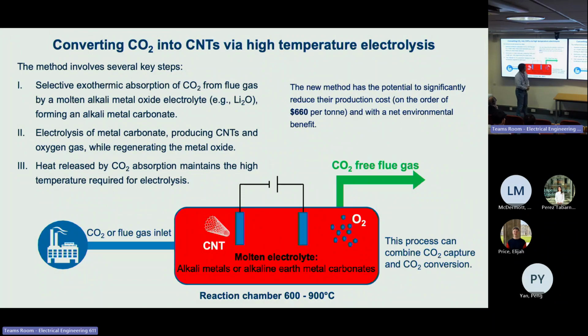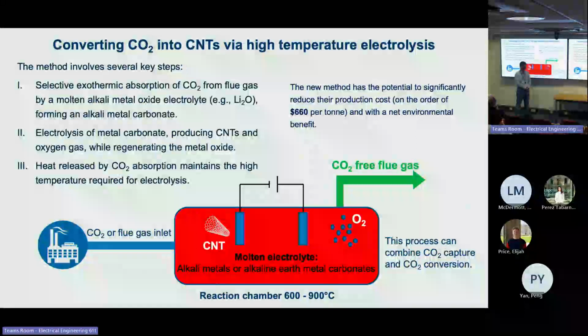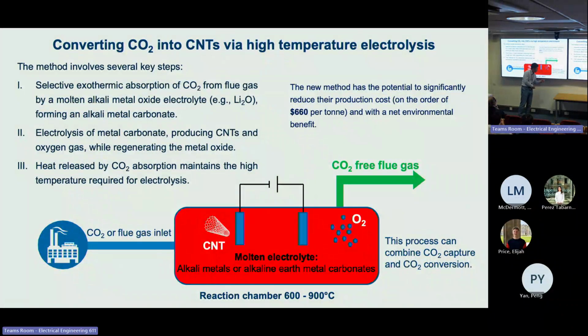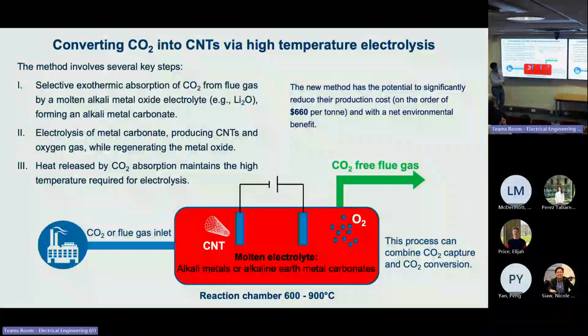So this new method has the potential to significantly reduce the production cost, on the order of $660 per ton. So we can say it's much less than CVD-produced carbon nanotubes. And also with a net environmental benefit, because we are consuming CO2 in this process. Another extra bonus of this process is that it can combine the CO2 capture and the CO2 conversion step. Usually CO2 capture and CO2 conversion are two separate systems, but this method can potentially combine them into one system.